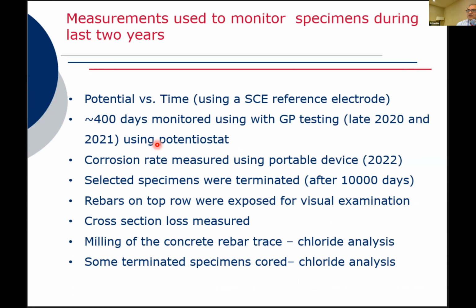We did some visual inspections for those that were terminated. We also used a vernier caliper to try to estimate the cross-section loss. And as I was telling you, in some cases we cored, and then we had several layers, and we were able to obtain the chloride profile. Also, from the piece of concrete right above the rebar, if the corrosion products were not all along the sample, then we did milling, and we obtained an estimated amount of the chloride concentration right at the rebar trace for some specimens as well.